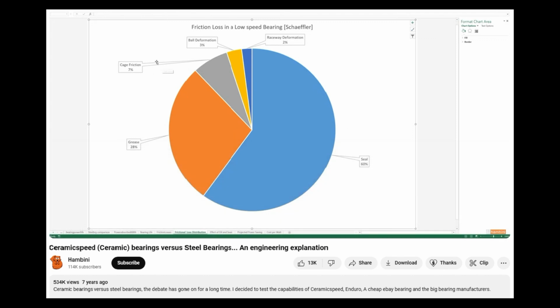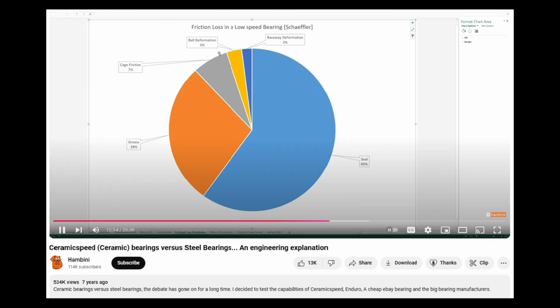So cage friction is the only element of friction inside a bearing where it's not a rolling movement, it is a sliding movement. So it's quite plausible that that's where most of the friction comes from. That's 7%. The ball deforming inside the cage is only 3%. So if you go from steel to ceramic, and the results show there's not much difference, that's the reason why, because there's only 3% of the total deformation.